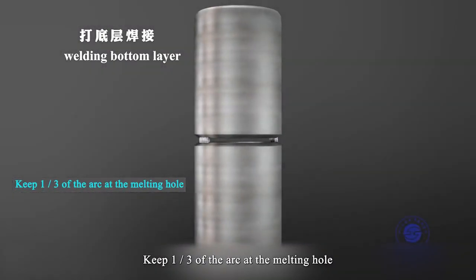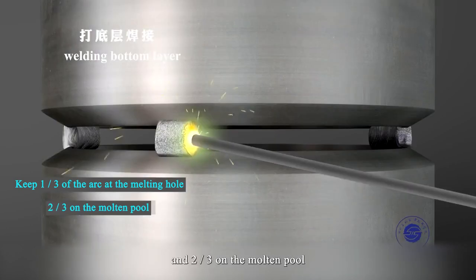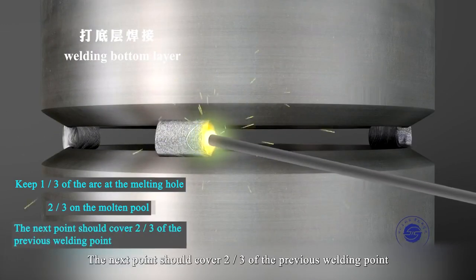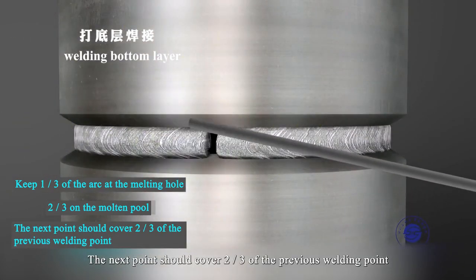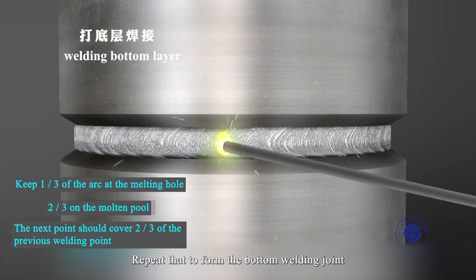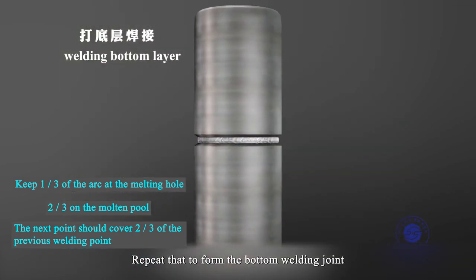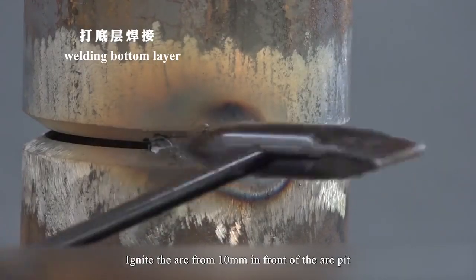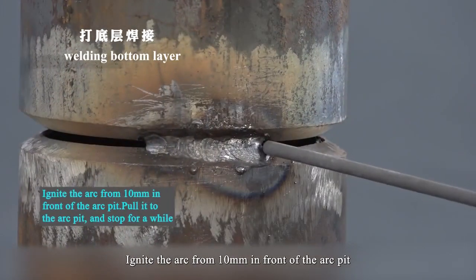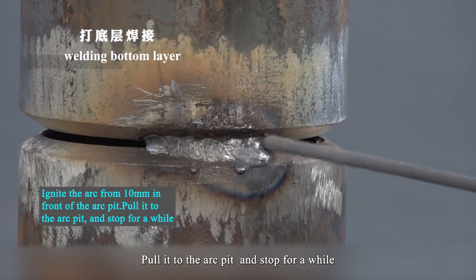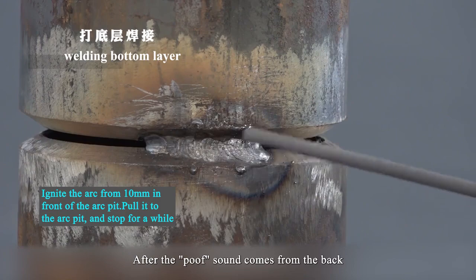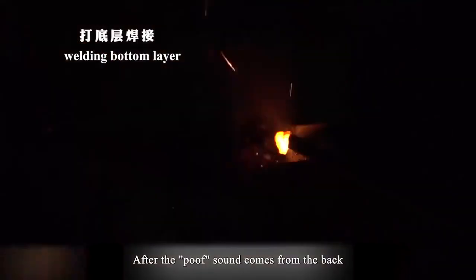Keep 1/3 of the arc at the melting hole and 2/3 on the molten pool. The next point should cover 2/3 of the previous welding point. Repeat that to form the bottom of the joint. The joint position should be cleaned. Ignite the arc from 10 mm in front of the arc pit. Pull it to the arc pit and stop for a while. After the poof sound comes from the back, turn to normal welding. When welding to the start, continue to weld forward for 3 to 5 mm to ensure the full filling of the joint position and the quality of the joint.